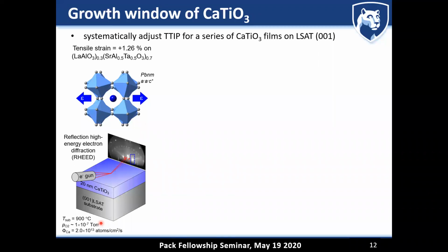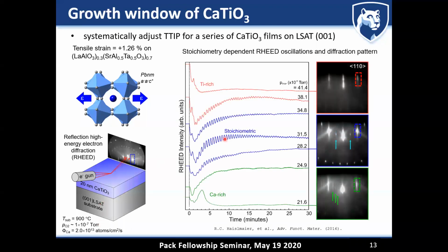And so if you calculate what density you would have for calcium titanate films, that boils down to a growth rate of about 25 or 30 nanometers per hour. And we can actually keep track of the growth rate using these RHEED intensity oscillations. Every time from one maximum to the next maximum is the completion of one entire layer of calcium titanate.